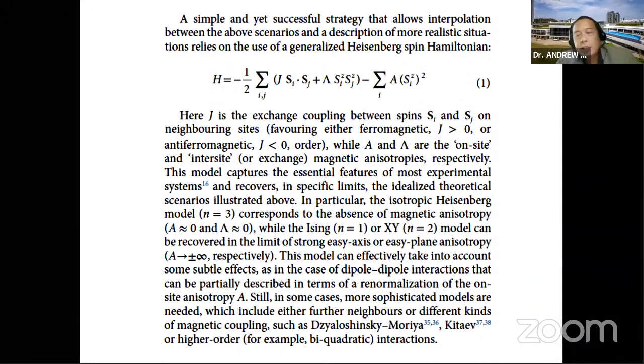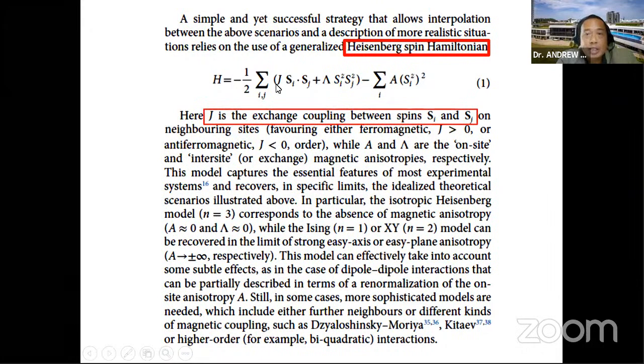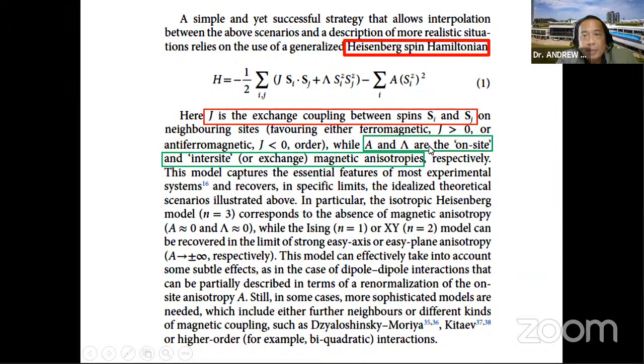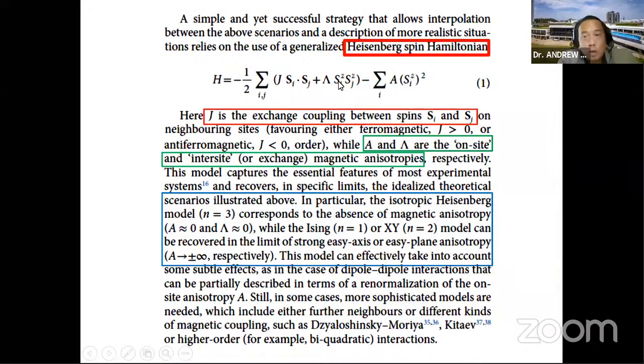So, okay, this is my last slide on the physics of it. Essentially, you can describe these 2D magnets using the Heisenberg spin Hamiltonian as shown. And you can see this is the Hamiltonian, and J is the exchange coupling between spins S_i and S_j, right? This is the spin exchange coupling term you always see in quantum mechanics. But in addition, there's A and lambda. A is the on-site, and lambda is the intersite magnetic anisotropy. So if you have some anisotropies, these terms come in, right? And you will see that in the isotropic case where n equals 3, A and lambda are 0, right? But for the Ising or the XY model, these are non-zero.